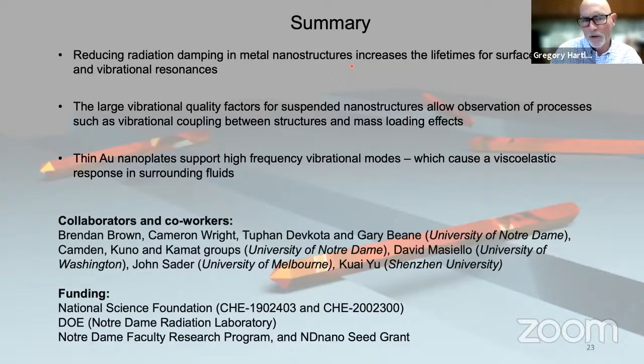For the acoustic modes, there's a large energy loss mechanism from radiation damping, from sound waves radiating out into the substrate. We can get rid of that effect by suspending the structures, and then you can create materials that have very long lifetime vibrational modes. And that allows us to look at processes like coupling between nanostructures and mass loading effects. And also when we go to very small, thin nanoplates that have very high frequencies, the long lifetimes help us measure viscoelastic effects in liquids and to show that they occur at the nanoscale. So for nanoscale materials, liquids behave quite differently than they do for macroscale materials because of the high frequencies they encounter.